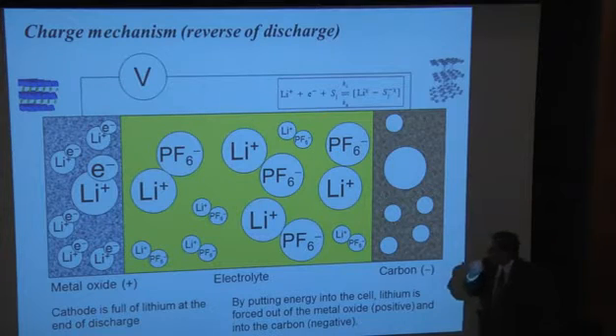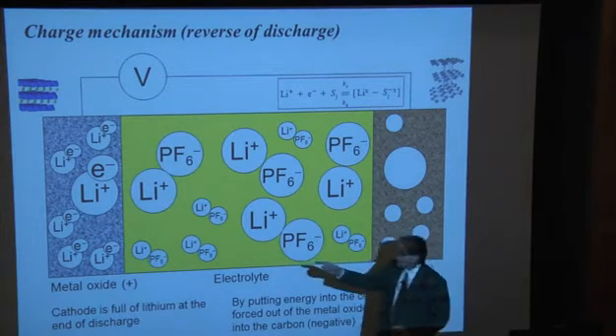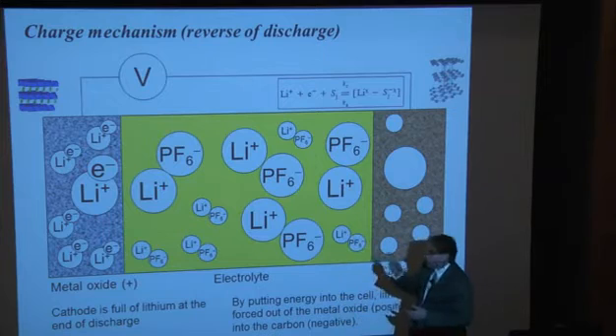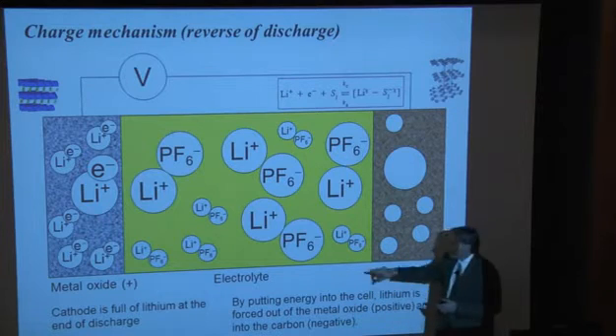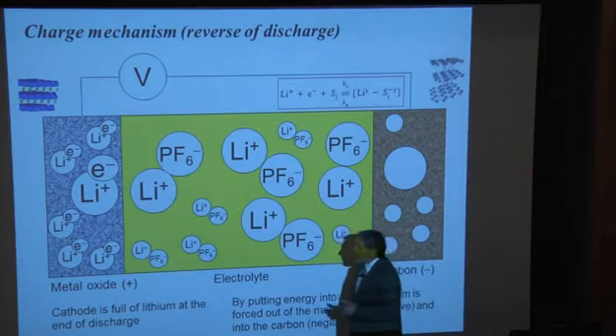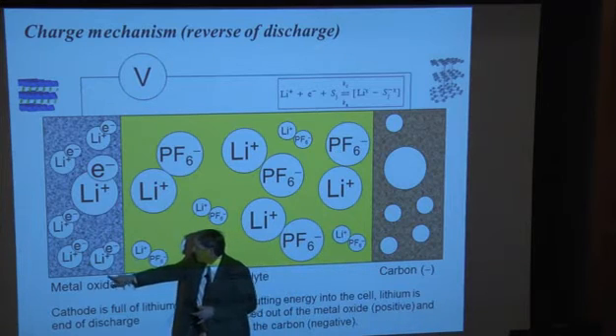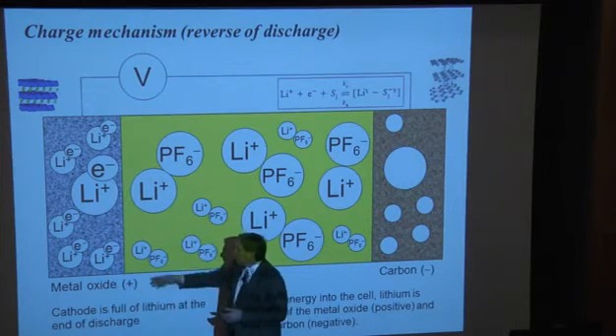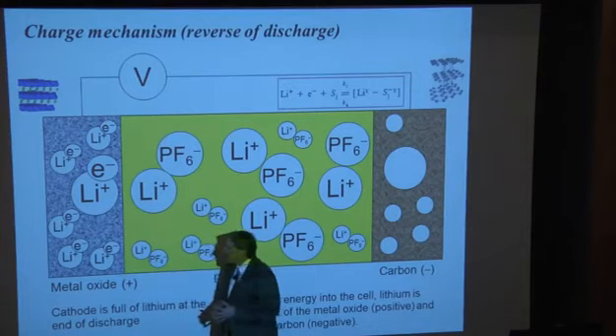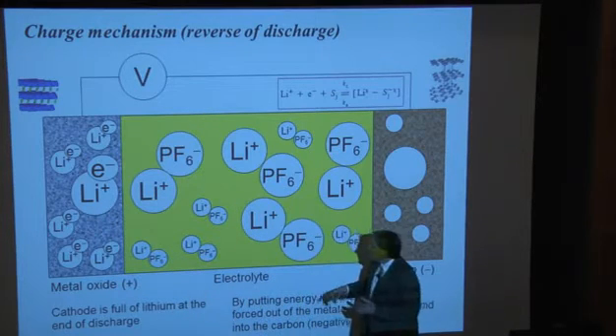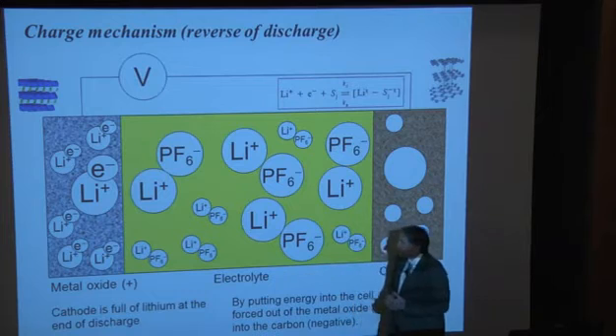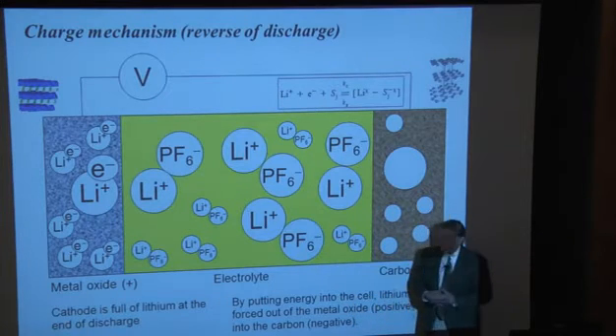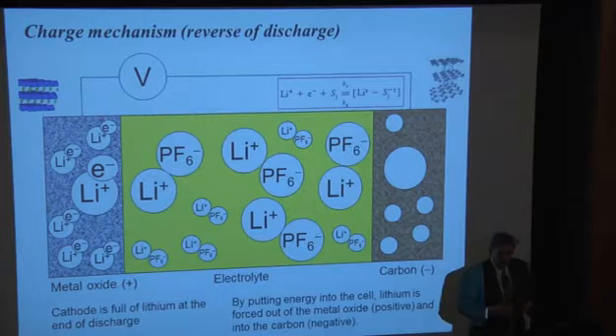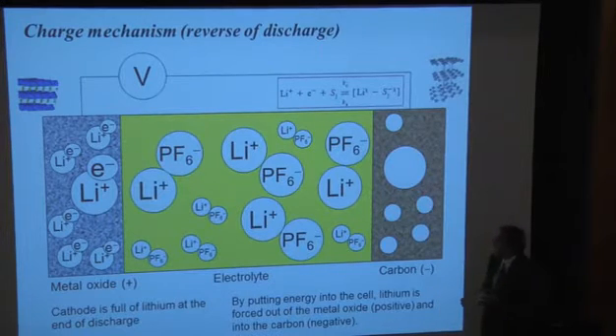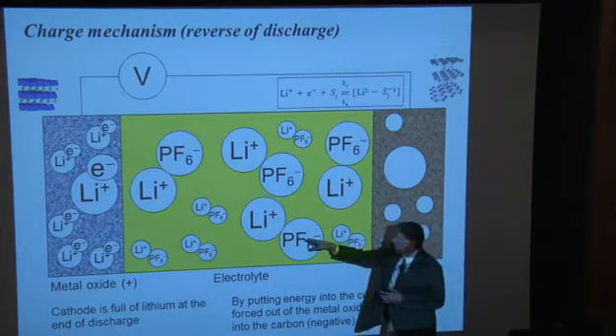As a lithium-ion battery is made, initially the lithium is housed in the metal oxide. That's going to be important. I'll talk about it in the next slide. And then you have an electrolyte phase. This isn't drawn to scale. This is typically about 50 to 100 microns in thickness. It's a porous electrode where you have inside of the active materials vacancies for lithium that can be filled. This is about 25 microns thick, the electrolyte phase. The yellow would represent solvent, typically diethyl carbonate and ethylene carbonate today. And the lithium ions, lithium hexafluorophosphate, are shown here.